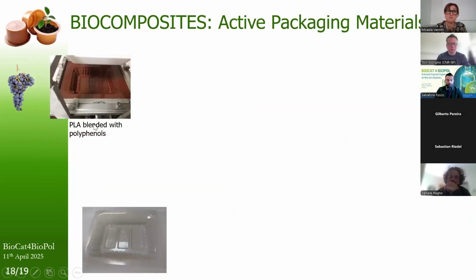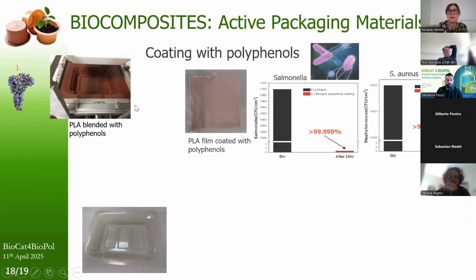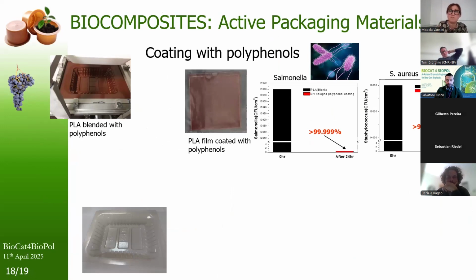Then we used polyphenols extracted from grape marc waste in blend with PLA to produce food trays. And then, in order to reduce the consumption of polyphenols and also maximize their effect, we tried to apply the polyphenols as coating on PLA films. And we obtained total antibacterial activity against Salmonella and also Staphylococcus aureus.